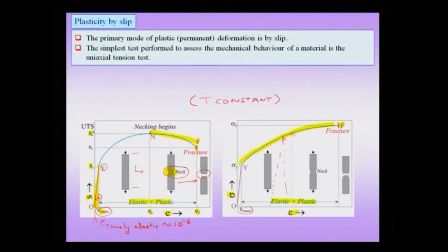So, to summarize these few slides, plastic deformation means permanent deformation, and slip and twinning are two important mechanisms of that. In normal deformation, like pulling of an aluminum rod under tension, it is slip which is the dominant form of deformation. One of the simplest tests we can do to understand the mechanical behavior of a material is the uniaxial tension test, which is typically plotted as an engineering stress diagram or a true stress true strain diagram. We can get important parameters regarding the mechanical behavior, like elongation to fracture and ultimate tensile strength, from these curves. The curve can be understood as macroscopically elastic and elastic plus plastic regions.